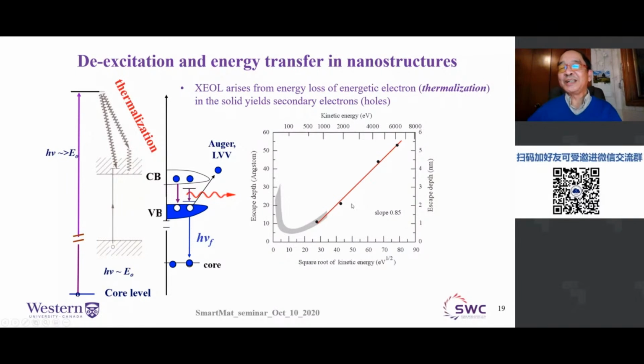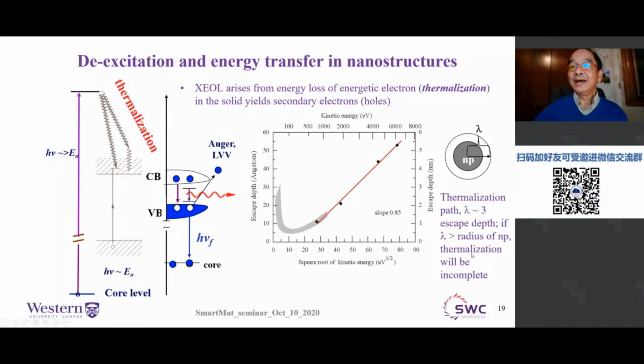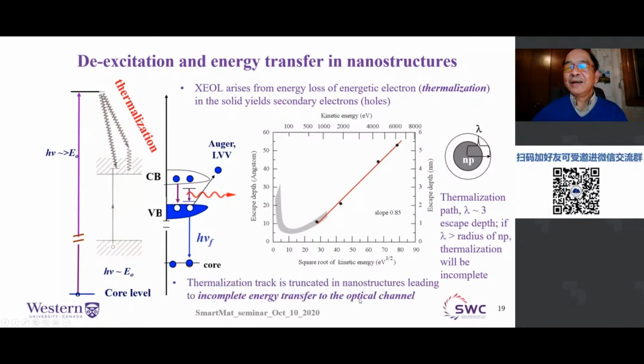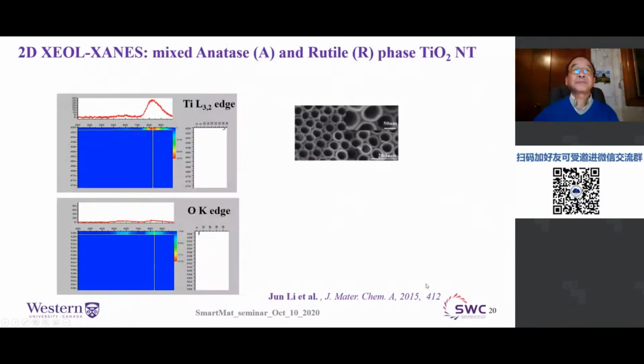So how do you understand thermalization? It's exactly the same way as people understand XPS, okay? So if I have a nanoparticle of this size, but my thermalization path is a lot longer than that, that means the electron will not be completely thermalized. That means the energy transfer to the optical channel is truncated, okay? And as a result of that, you have nanocrystals of different size. Their response to converting X-ray into visible light is different, okay? And this is the most interesting part about nanostructures and XEOL.